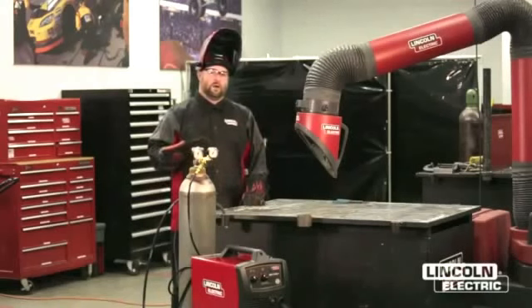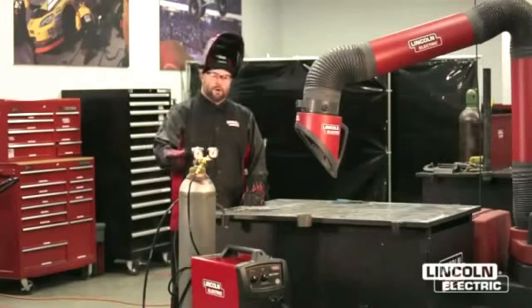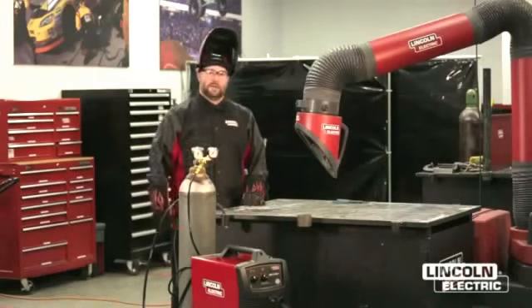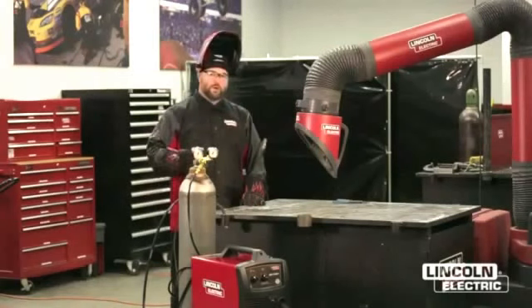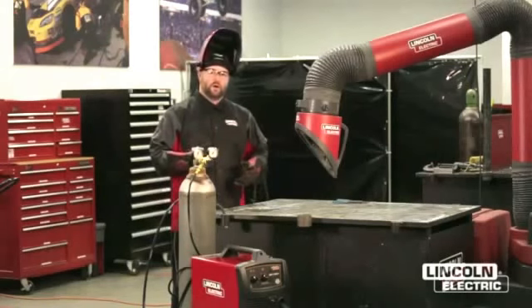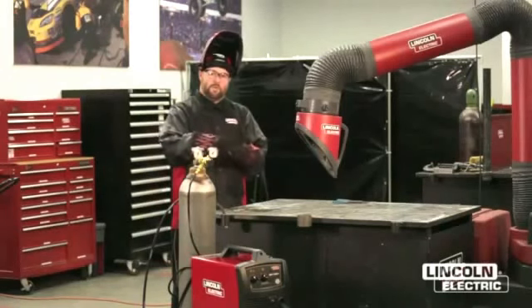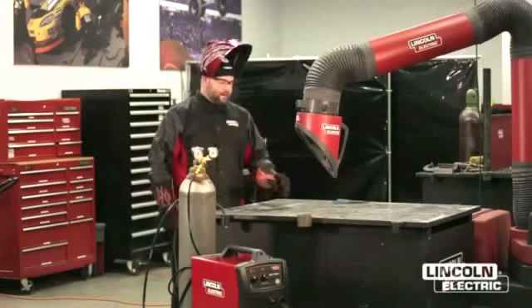Remember, as you increase your wire feed speed, the puddle gets hotter. You're going to increase the heat and amperage into your weld. So we're going to start and see what happens when you have too much wire feed speed. What you're going to notice is the wire is going to start to stub, and you're going to have to go back and adjust from there.